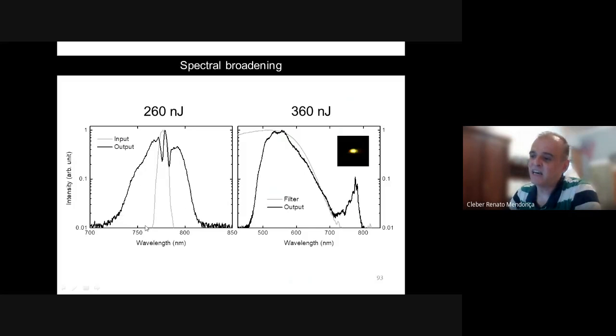So here the gray line is the spectrum of the laser I'm injecting in my Gorilla Glass waveguide. And then when I increase the power, I generate much more spectrum by a process which is called self-phase modulation, which is also a nonlinear process related to Chi-3 nonlinearities. Then if I now increase even more the intensity of my laser that's coupled to the waveguide, you can generate white light in the waveguide. So you can actually generate and guide the white light.